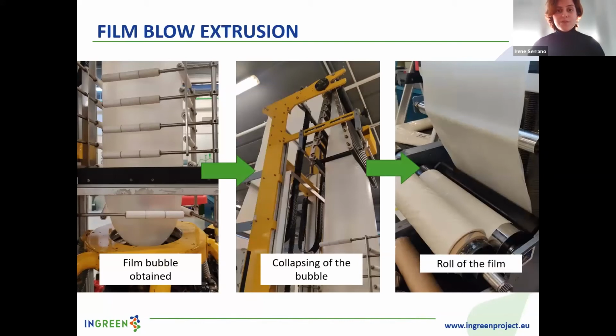Then, after passing through the screw, the molten polymer is forced through a vertical ring-shaped die to form a thin walled tube. Air is injected from the center of it, making it expand and creating a bubble. This bubble gets cooled down by air, while it's pulled up by a series of rolls that are placed at the top of the film extrusion machine. Then these rolls collapse the bubble, giving it its final planar shape. And the newly formed film is taken down from the top of the film extrusion machine, guided by a secondary series of bars, and it is wound up into rolls that will serve later for the production of the bag-in-box prototypes.